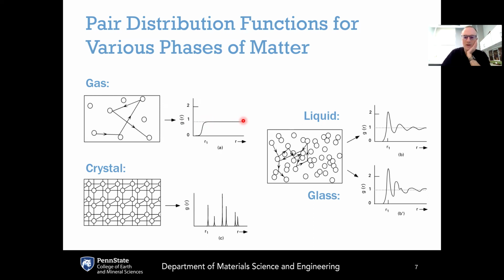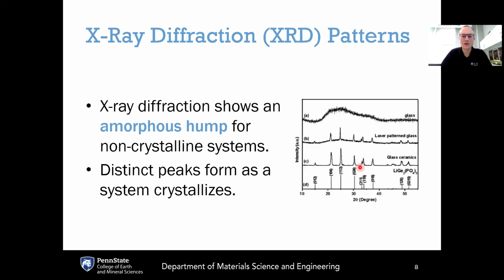Now, if we're in the liquid state or the glassy state, here we are somewhere in between these two extremes. The short range order here for the first nearest neighbor is well defined. That gives us the first peak. The second nearest neighbor is somewhat well defined. Maybe you'll have some evidence of a bit of ordering at the third nearest peak, or maybe not. And then after that, it will converge to 1. You'll also see that the pair distribution functions of the liquid state and the glassy state are very similar because the structure of the glass is essentially the frozen-in structure from the liquid.